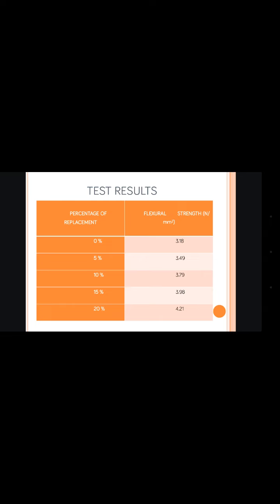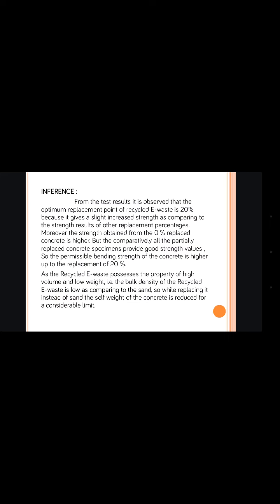The reason why we did not go above 20% is because, after referring to a lot of journals, we found that beyond 20%, the concrete begins to lose its compressive strength. So our test results are a straight line graph, a gradual rise. So what's the conclusion, the inference? The inference from this test result is that the optimum point of replacement of e-waste is 20%.